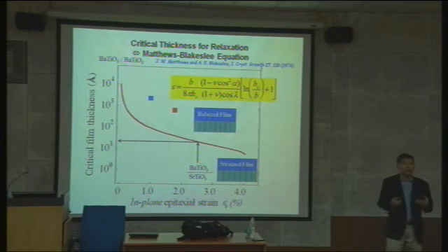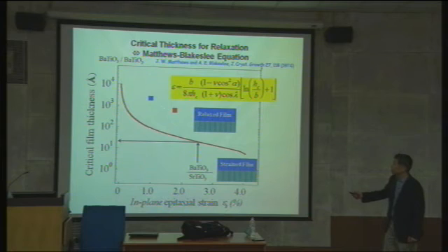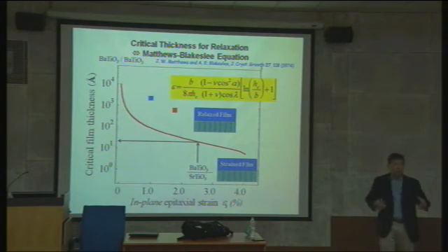How did we test it? We used X-ray diffraction. With X-ray diffraction, we can tell what the lattice parameter is and whether the film is fully coherent or not. We looked at this, and the equation is generally correct. It follows this line, but the absolute value is not correct. So it's a good guideline, but not necessarily correct number-wise. Based on this Matthews-Blakeslee equation, in this region everything is relaxed, and below this region everything is coherent. But with a new curve, maybe the curve follows here, and the region of coherent strained film growth can be broader. Okay? So now, this is very encouraging.